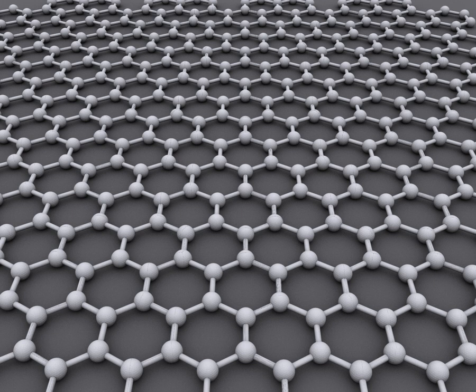The atomic structure of isolated, single-layer graphene was studied by TEM on sheets of graphene suspended between bars of a metallic grid. Electron diffraction patterns showed the expected honeycomb lattice. Suspended graphene showed rippling of the flat sheet, with amplitude of about one nanometer. These ripples may be intrinsic to the material as a result of the instability of two-dimensional crystals, or may originate from the ubiquitous dirt seen in all TEM images of graphene.